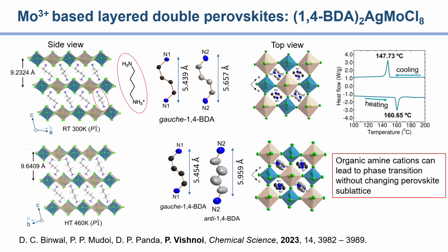So here, I'll again slightly change the direction. What I mentioned so far, we used methylammonium as the cation, and then I briefly showed a replacement of methylammonium with cesium to tune the dimensionality from 1-dimensional to 3-dimensional. Now, apart from these cases, one can change the cation to a very long cation, here a diammonium cation. And this will basically break the halide bonds along one of the axes because it's a linear cation. So the remaining lattice will be a 2-dimensional lattice, which is corner connected in the AB plane.